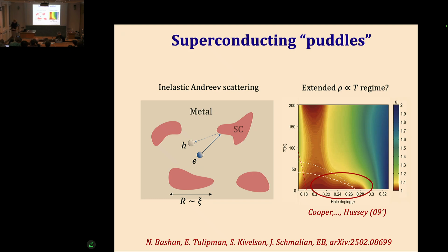Very, very roughly speaking, the picture is that as we vary doping, the density of these islands is changing, and that's why the slope of the linear T resistivity is changing. But that's also why TC and HC are changing. So roughly speaking, when the distance between these things is of the order of a magnetic length, some fraction of a magnetic length, or a thermal length, that's where TC is, or HC.